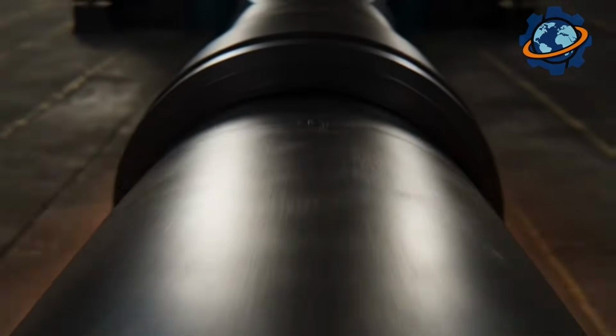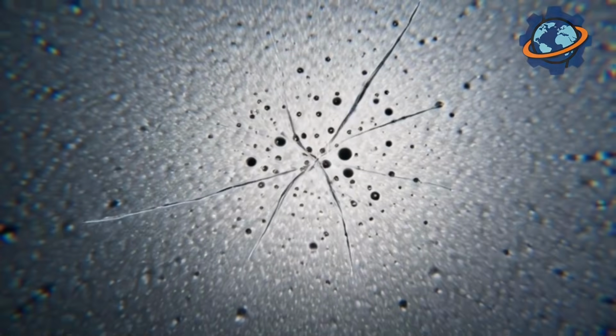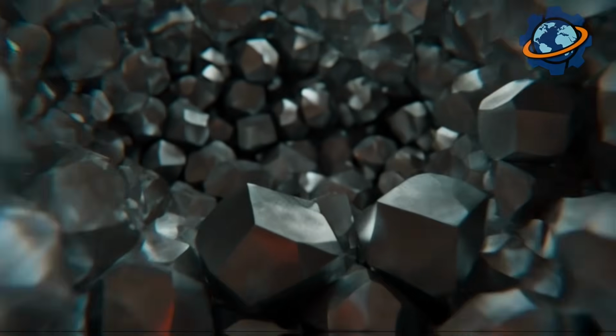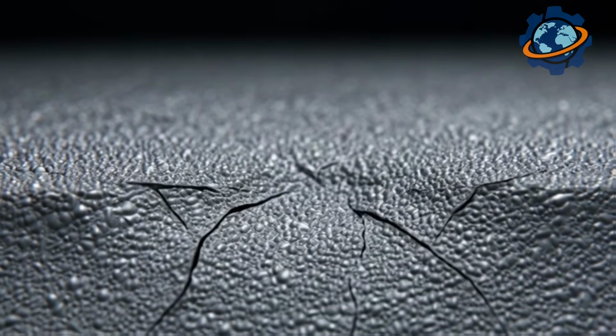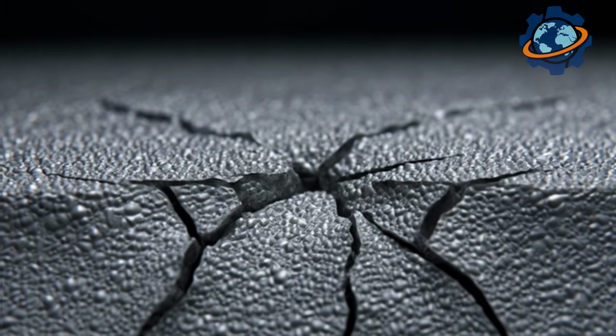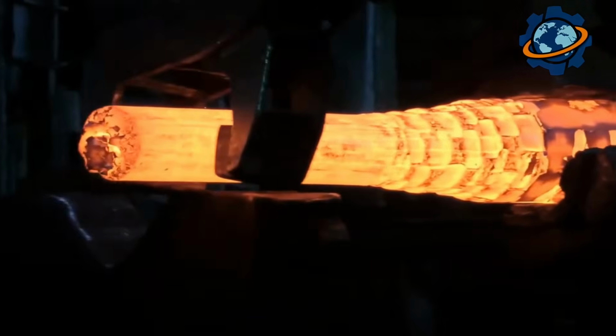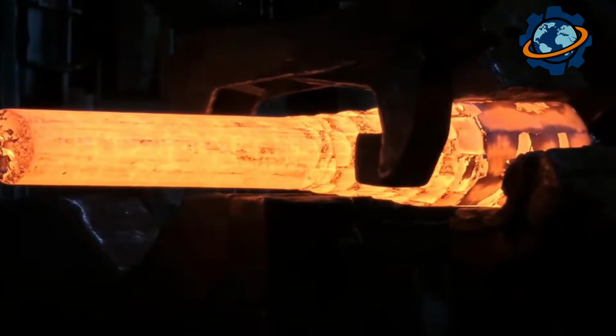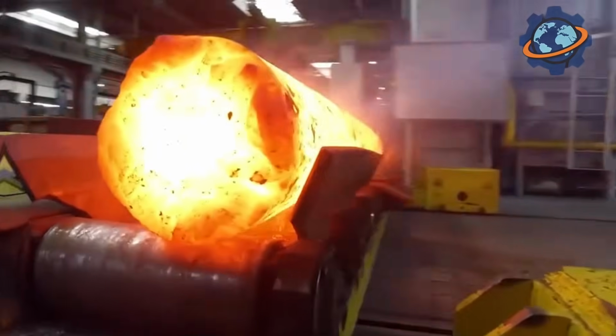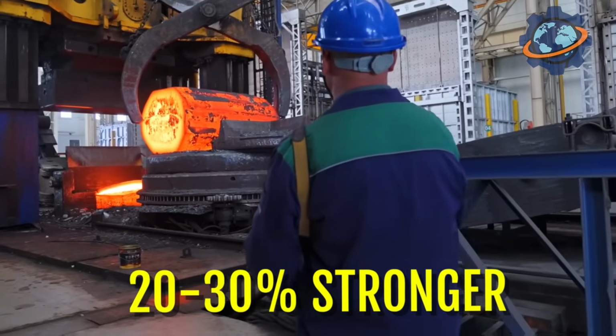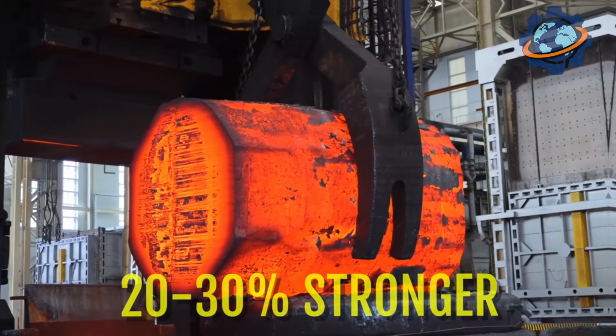Under the press's pressure, the steel's crystalline structure reorganizes. Large grains break down into smaller ones, micro cracks close up, pores flatten and weld shut. It's like healing a wound. Under pressure, the defect's edges fuse together, and the metal becomes solid. After forging, the steel becomes 20 to 30% stronger than cast metal.